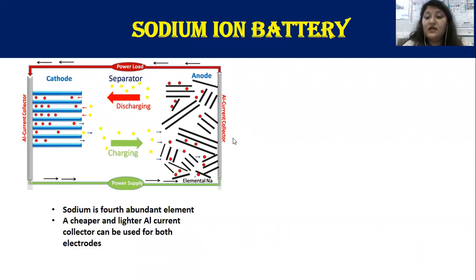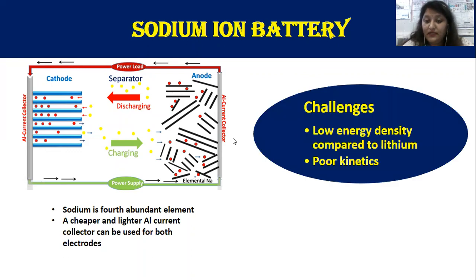The structures, components, and charge storage mechanism are similar to the lithium-ion battery, except the charge carriers are changed from lithium to sodium ions. The major challenge of sodium-ion batteries is the low energy density compared to lithium-ion batteries, and the larger sodium ion size of 1.02 angstrom compared to lithium ion, which is 0.76 angstrom, which limits the diffusion of sodium ions to insert into or extract from the host material, thereby influencing the overall kinetics and electrode integrity.